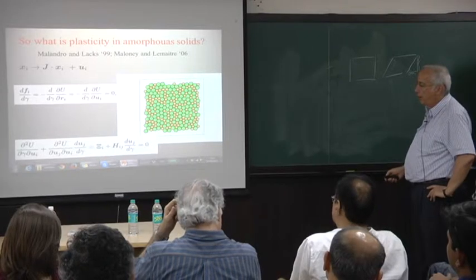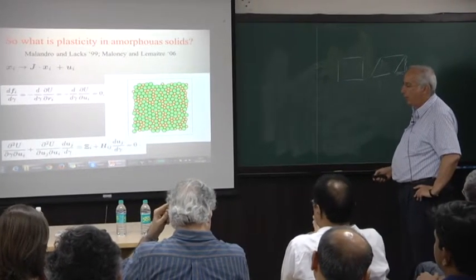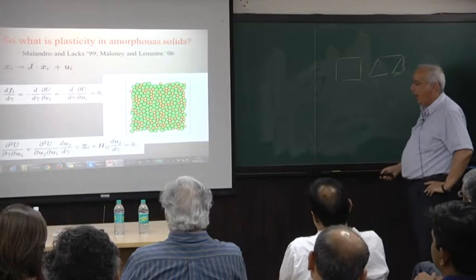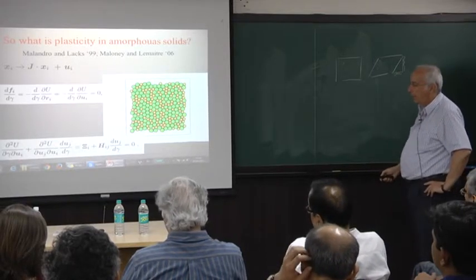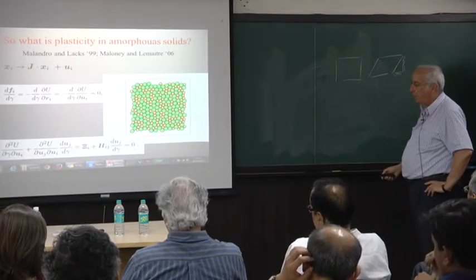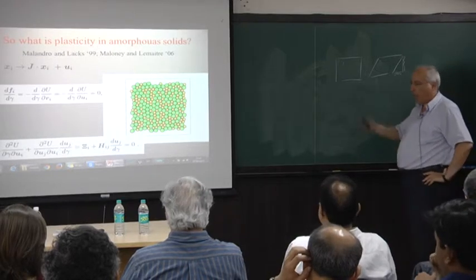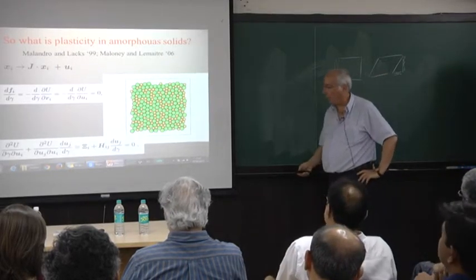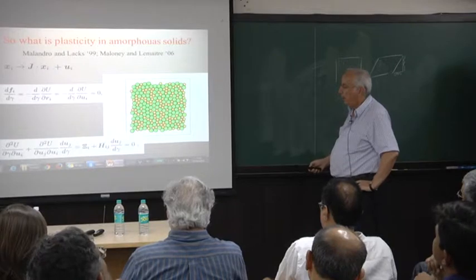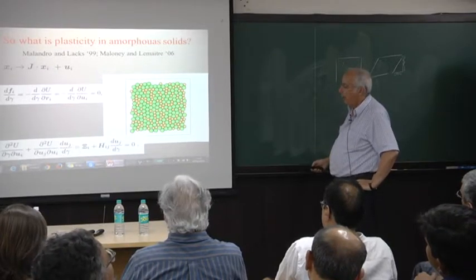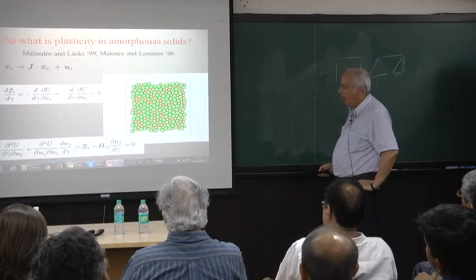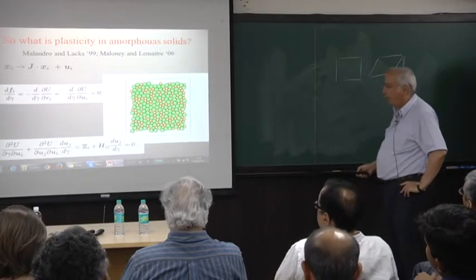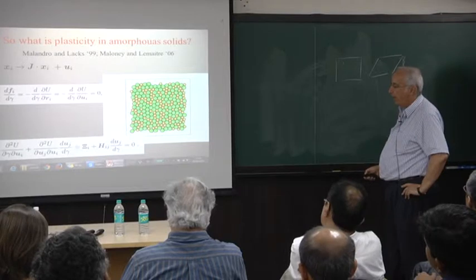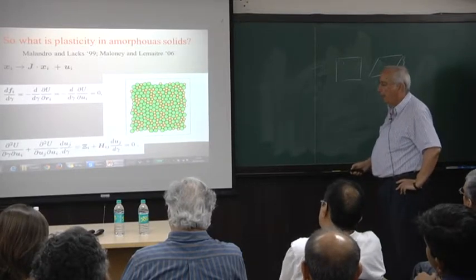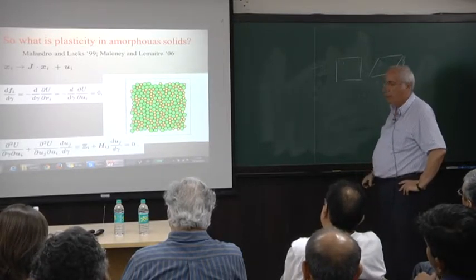Now that's very nice, because what did I now discover in this condition? This matrix, d squared U dUj dUi, is a well-known matrix known as the Hessian matrix Hij. This object has only one index, so it's a vector. We call it psi i, and this is known somewhere in the literature as the non-affine force. And now I have a formal equation for how much dUj d gamma I have. If I could now invert this equation, if this matrix doesn't have zero eigenvalues, I can invert H and find what is the non-affine thing.